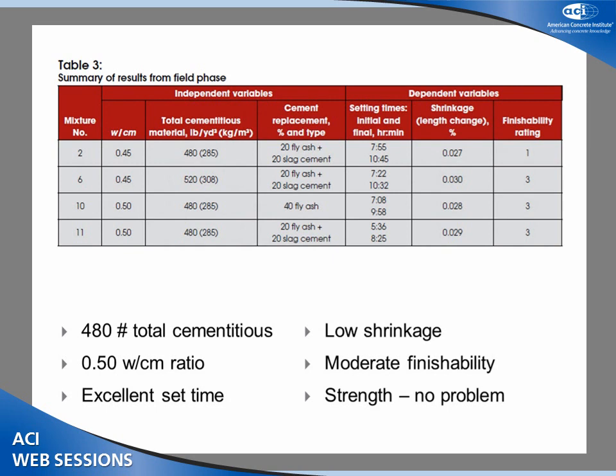All right, moving right along. These are the 4 highest performing mixes that we actually put out in a Target store in Inver Grove Heights here locally. We got some contractors to work with us and had very good results with these. Number 11 ended up being our highest rated mix: 480 total cementitious, 20% fly ash, 20% slag, water cement ratio of 0.50. Now, some of you might say that's pretty high.